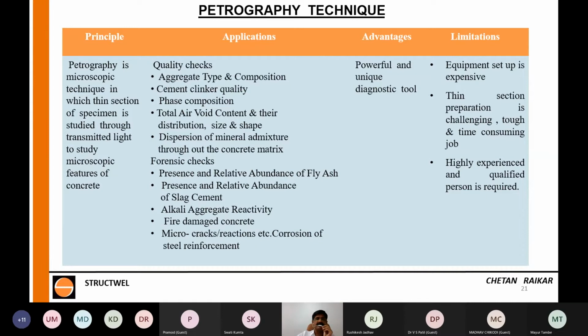Presence and relative abundance of fly ash, presence and relative abundance of slag, alkali aggregate reactivity, fire damaged concretes, again very useful in AAR and fire damaged concrete. You know, micro cracking and corrosion reactions. Again, see, these are the various applications, very powerful and unique dimensions. The limitation is that equipment setup is expensive, and you require a highly experienced and qualified person. This is extremely important because seeing it under a microscope is easy, but the interpretation is very difficult, and you need several years of experience to do this.